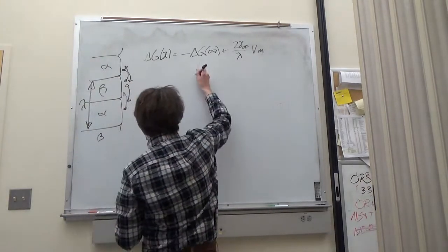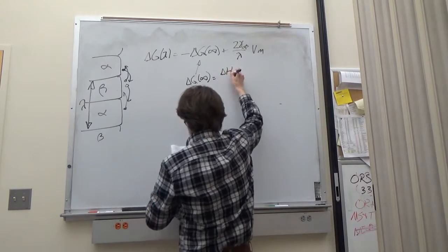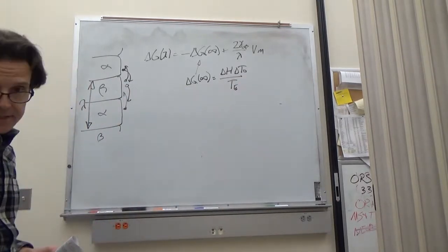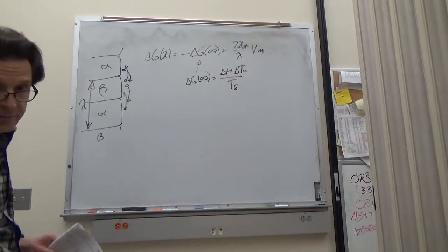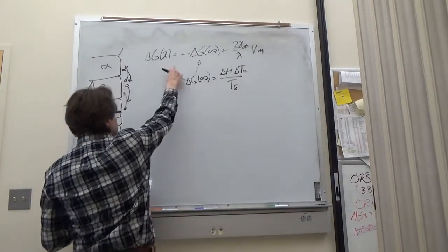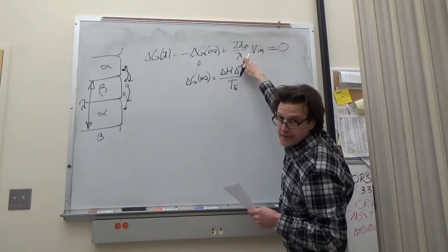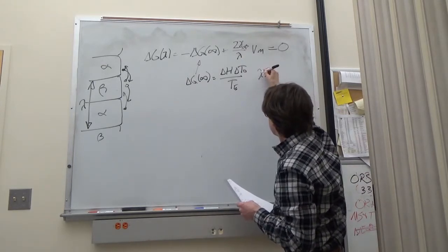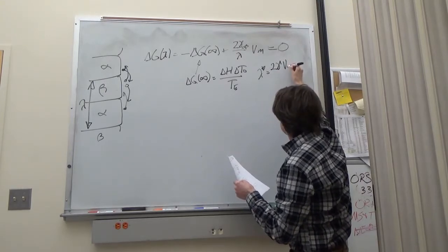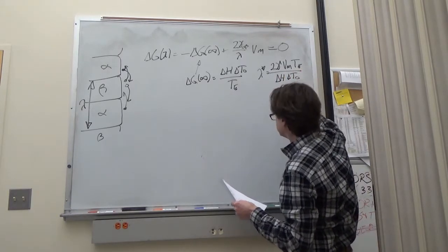And using that, which we had before, is just the latent heat multiplied by the undercooling and divided by the transition temperature, in this case the eutectic temperature, and setting this equal to 0, we can solve for the critical size lambda, and we got lambda star is equal to 2 gamma Vm, the eutectic temperature, divided by delta H delta T0.